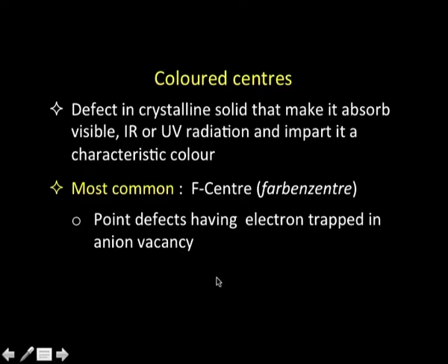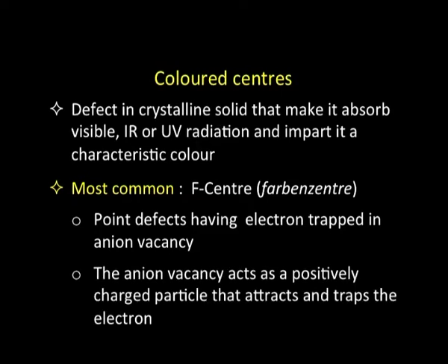That means we have an anion vacancy and an electron occupies it. Such a situation is referred to as an F center. This anion vacancy where the electron is captured acts as a positively charged particle which attracts the electron towards itself and traps it, and that electron trapped in an anion vacancy is an F center, and that is what is responsible for the color of the material. We will look into this.